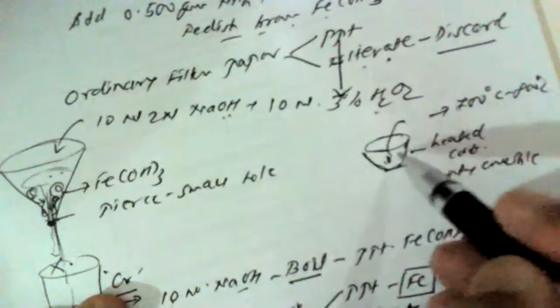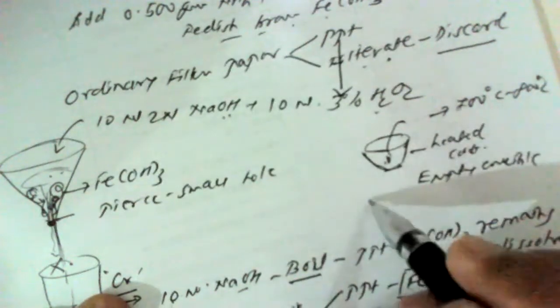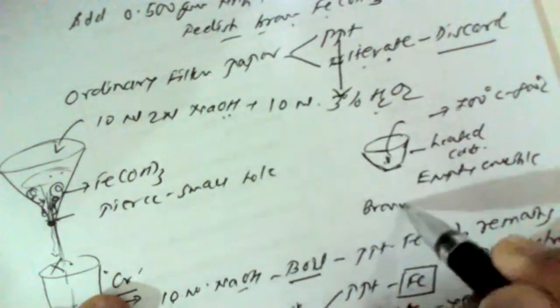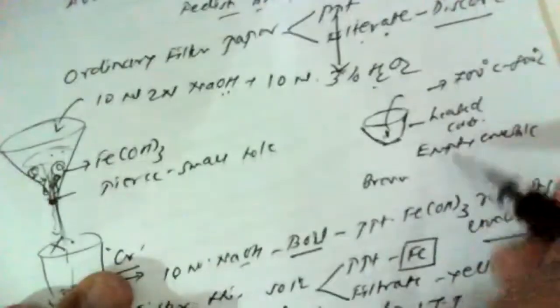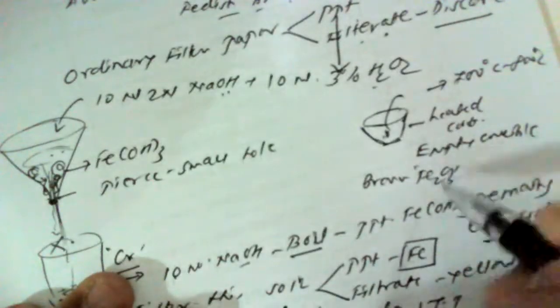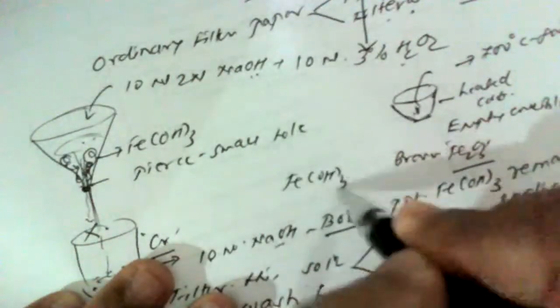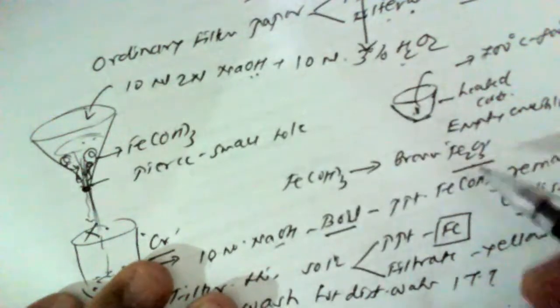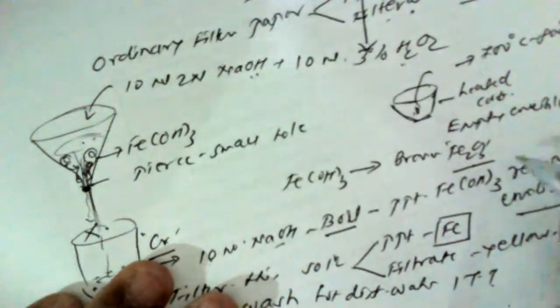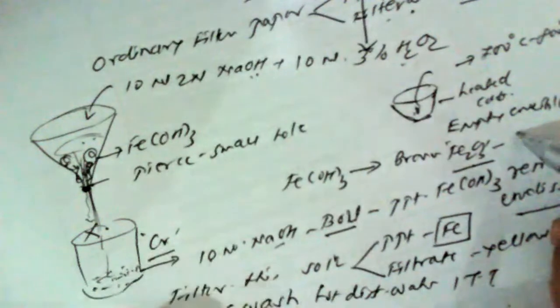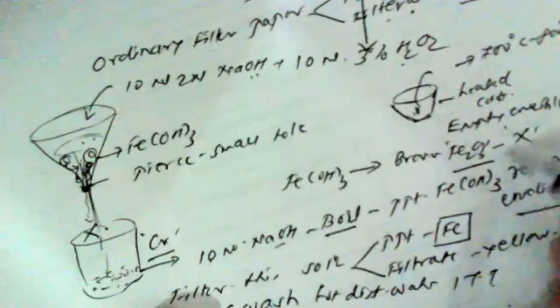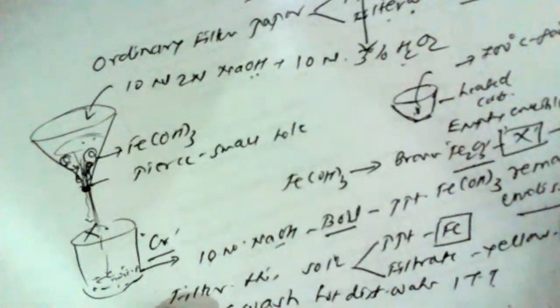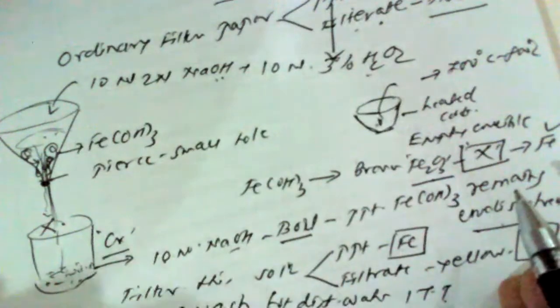When complete burning of the paper takes place, we obtain brownish colored crystals, which are ferric oxide. So we have converted ferric hydroxide into ferric oxide by the removal of moisture content, and by taking the weight of this residue, which we call X, we can calculate the quantity of iron. This is how we can calculate the quantity of iron.